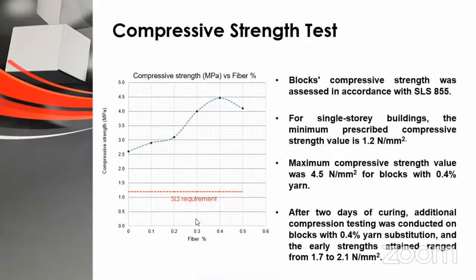Blocks were assessed using several tests in accordance with the SLS 855 standard. Compressive strength has a significant impact on the performance of cement blocks and ensures the general quality of the finished product. The minimum recommended compressive strength value for a one-story building is 1.2 Newton per millimeter squared. The maximum compressive strength value was 4.5 Newton per millimeter squared for blocks containing 0.4% yarn, as seen in the graph, which shows how strength varies with the fiber content. Additional compression testing was done on blocks with 0.4% yarn substitution after 2 days of curing, and the early strengths achieved ranged from 1.7 to 2.1 Newton per millimeter squared.